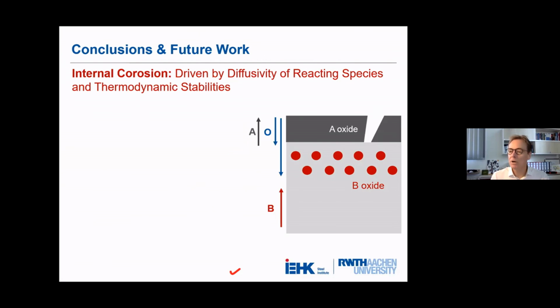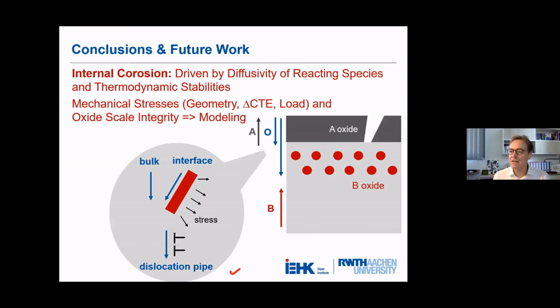So I hope I could show you in which way internal corrosion is driven by the diffusivity of the reacting species and thermodynamic stabilities. And it's strongly influenced by mechanical stresses. These mechanical stresses can be due to the geometry, for instance, at edges. So we have growth stresses of the oxide, or the difference in the coefficient of thermal expansion, also applied loads, which cause cracking of the oxide, and then an increase in inward diffusion of the corrosive species like oxygen or nitrogen.